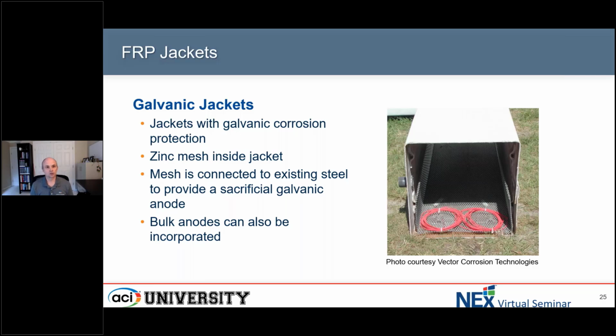Then there are also jackets that incorporate some type of galvanic protection. So this is a photo that you see there. This is a fiberglass jacket that has a zinc mesh on the inside of it. The zinc mesh is electrically tied to any steel element, so say reinforcing steel in a reinforced concrete element would be electrically tied to that reinforcing steel to provide galvanic protection to the steel. So the mesh would corrode sacrificially to the steel corroding, much like we do in a lot of other concrete repair applications where we use galvanic anodes to help mitigate corrosion. These can also be incorporated into these jackets to provide more robust corrosion protection.